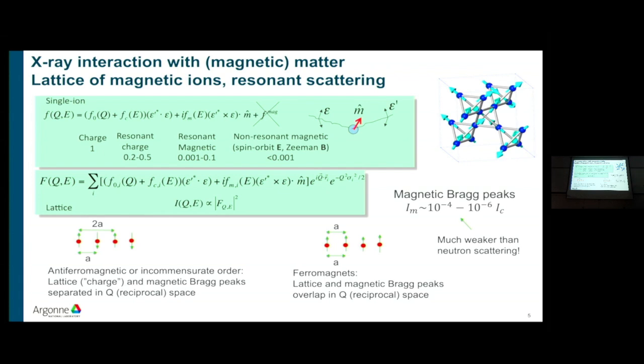The intensity is the cross-section, an area, which is the square of R0. And this is the intensity that you would measure in an experiment. So it's a square of this sum of terms. Now, we said that the resonant magnetic scattering is small, could be 0.1%, could be less, could be even 0.01%.